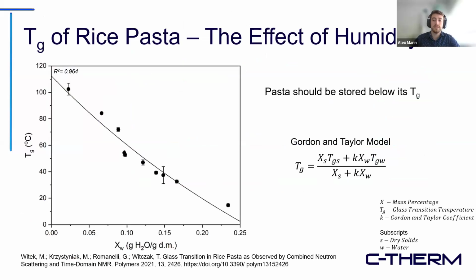This was a study done on DSC. The researchers made rice pasta and then they exposed it to different levels of humidity for time. They then used DSC to determine the glass transition of the pasta. They then compared their data to a model called the Gordon and Taylor model, which looks at the pasta as a binary system of the dry solid and the water that it took from the ambient humidity.